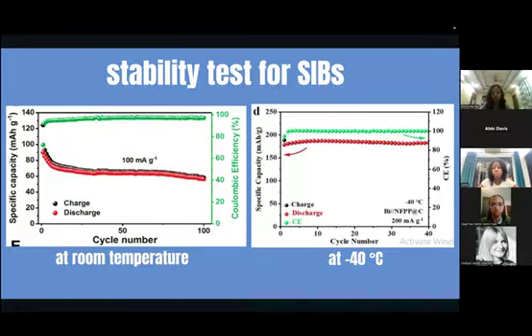And the second graph on the right is showing the cycling performance of a sodium-ion battery at a very low temperature of minus 40 degrees Celsius. So some key observations for this graph is that the battery has high specific capacity maintained, and it also has cycling stability, with capacity values nearly flat across cycles, showing good stability over time. And lastly, the battery shows high Coulombic efficiency of about 95 to 99%, indicating very little loss of charge per cycle.